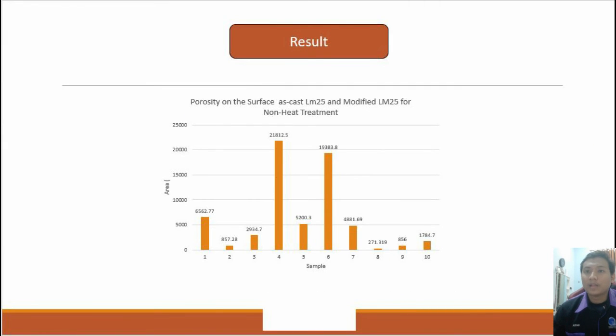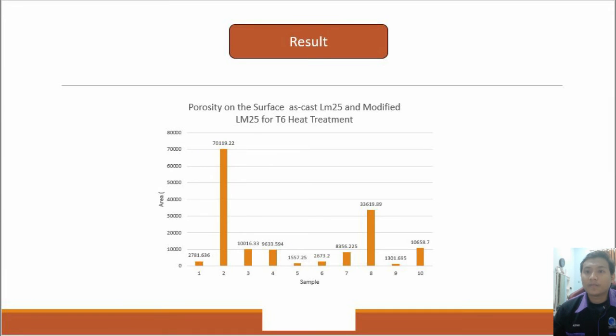Based on the graph shown, the largest area of porosity formed at the center of the surface area for non-heat treatment is sample 4, while the smallest area of porosity is sample 8. Next, the largest area of porosity formed at the center of the surface area for heat treatment is sample 2, while the smallest area of porosity is sample 9. Based on the result, we found that it is opposite to the Shabestari statement. This is because of a lack of method used in collecting the data, or improper and inconsistent method while pouring the molten alloy into the mold.